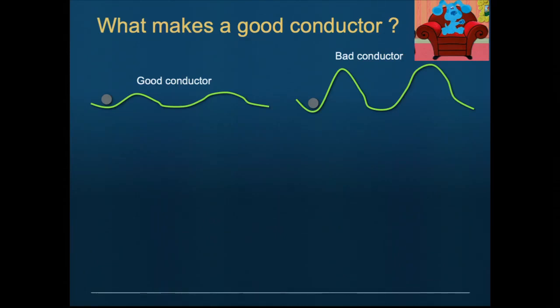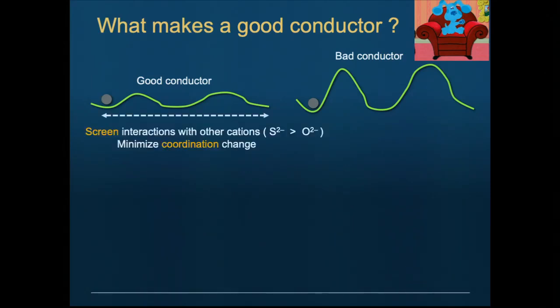Well, what you want to do as this ion moves, right, is minimize the change of interaction with the rest of the structure. Because it's all about how flat the energy landscape is. So if you never change the interaction or have low interaction in general, then you can make a good conductor. So the first thing you do is you want to screen the interaction with the other cations, right? Because there are other cations around that give you electrostatics.